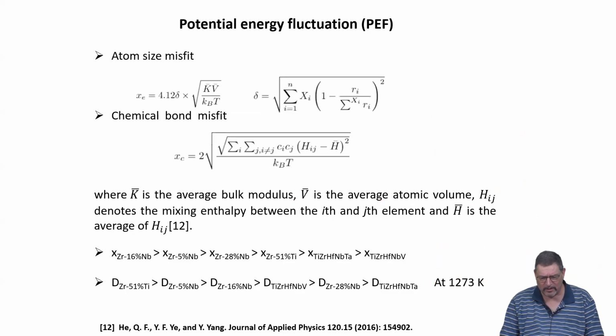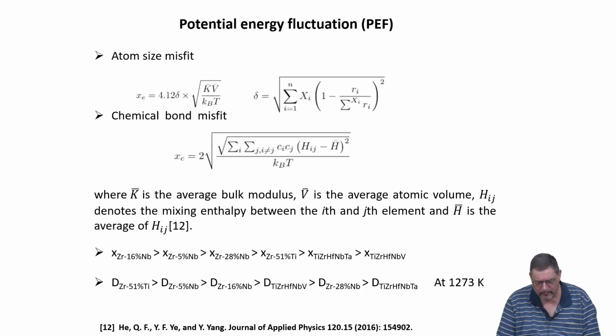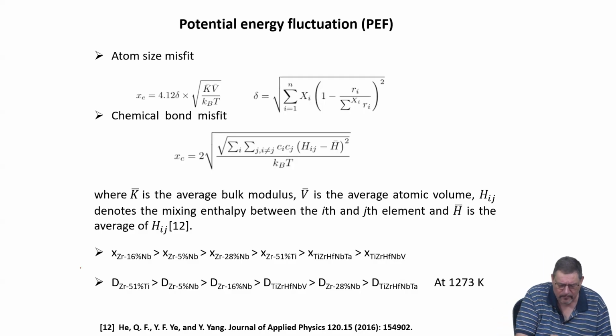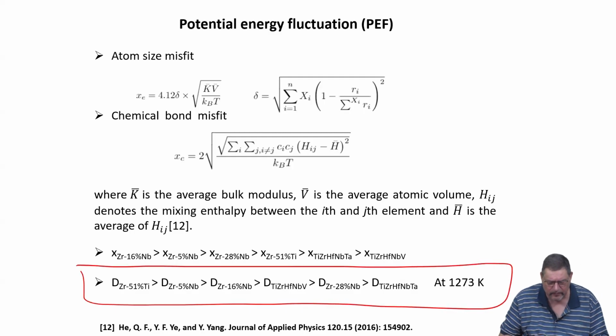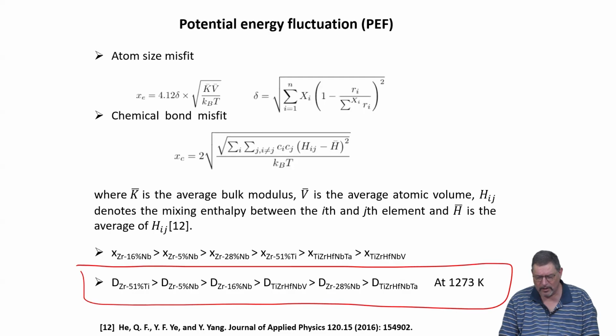So when we now calculate based on the atomic size misfit, and we have already introduced how to do that, these are the given equations, and from there also calculate the chemical bond misfit, which is indicated here with these average bulk modulus, average atomic volume, and the mixing enthalpy between the different species. Then we would get to this sequence of diffusion coefficients in this alloy, right? So the diffusivities in these rather not high entropy systems would be larger as compared to the high entropy system at this temperature.